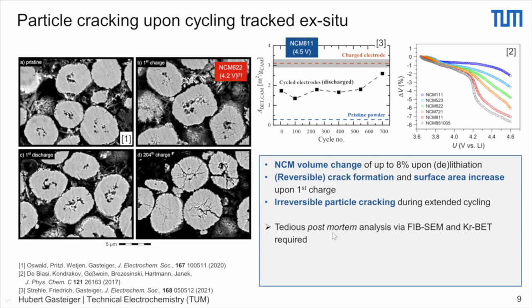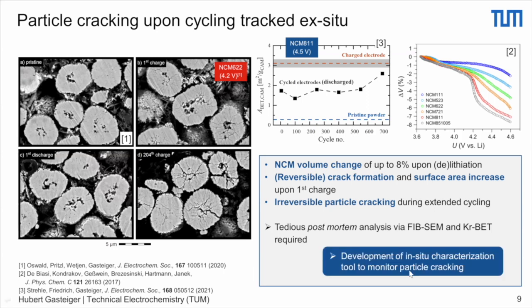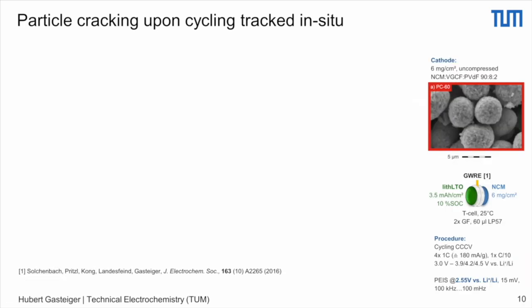This, of course, is very tedious because doing FIB-SEM is a big effort, plus also it cannot be quantified. And the krypton BET, of course, requires a lot of experimentation to harvest electrodes, put them in the BET and so on. So what we wanted to do is to see whether we can follow this with our capacitance-based method. And so this is shown here on the next slide for an NCM material, 622 NCM. And we utilize for this a gold wire reference electrode. So something we had published before, where essentially you insert the micro-reference electrode between the two electrodes.